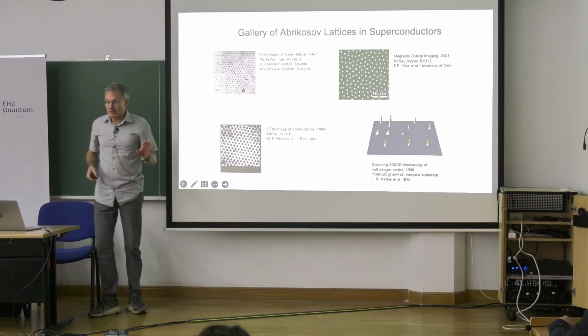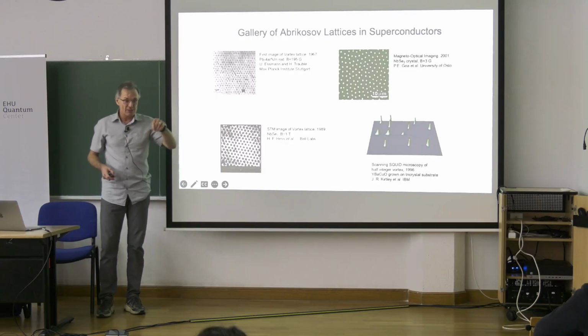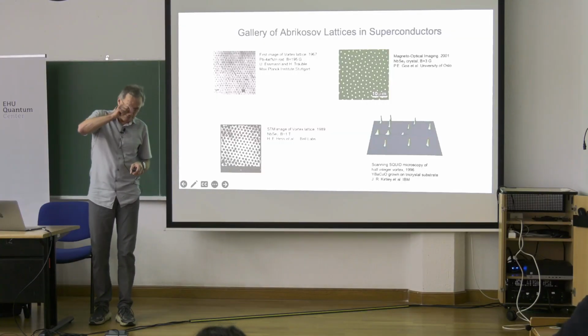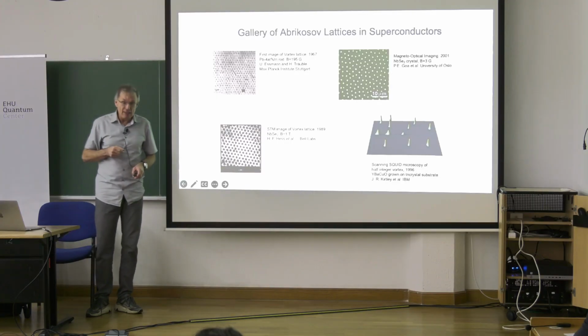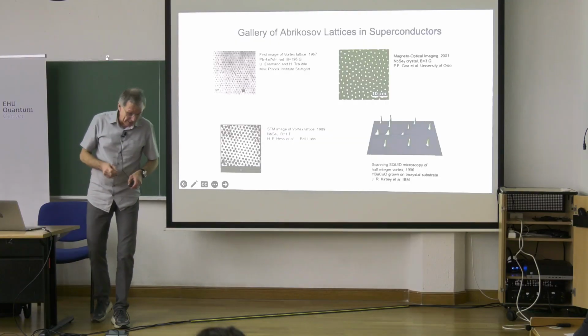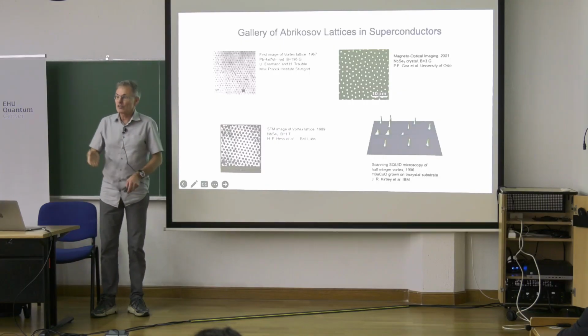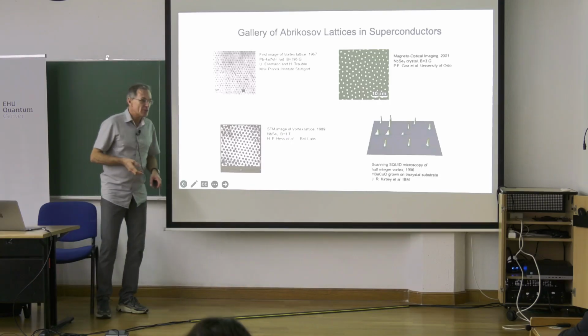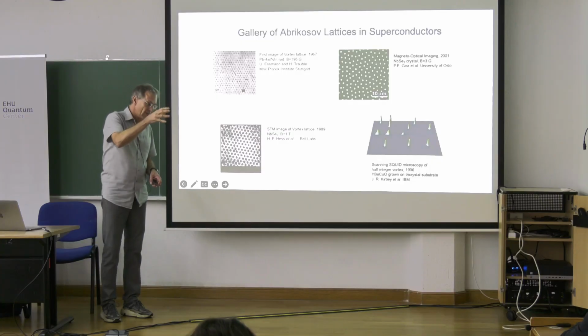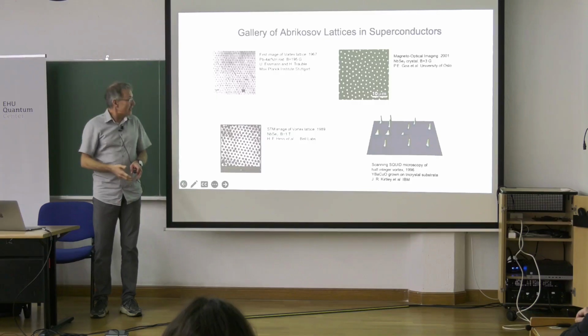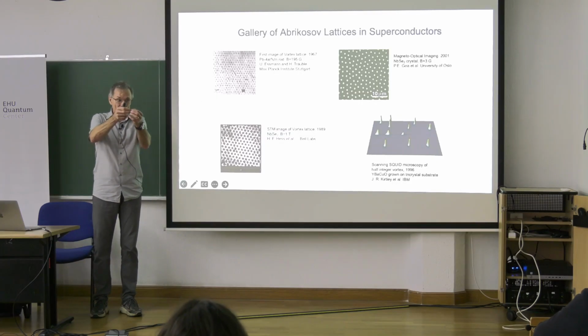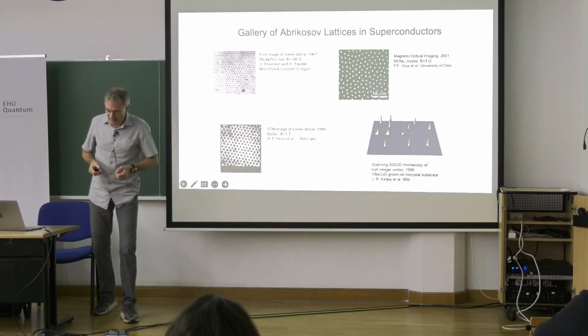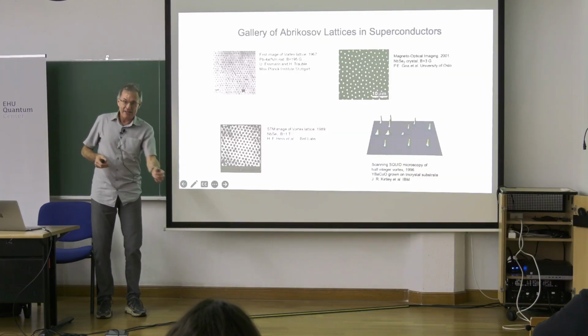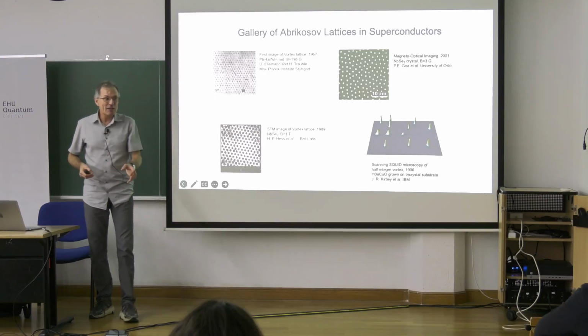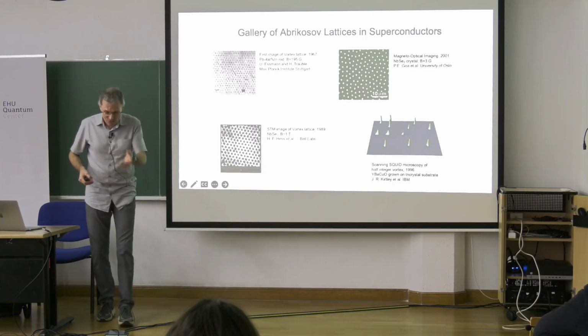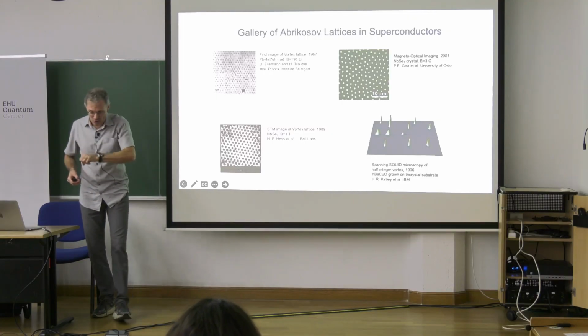It's far from trivial to realize technically, because these magnetic particles, you don't just sprinkle them. In the experiment, you have a Wolfram wire, tungsten wire, like in an old-fashioned light bulb. You push a strong current, which heats it to a few thousand degrees, then it's hot and emits particles, which then come to the surface of your superconductor. So in the same setup, you need this tungsten wire, which is more than 1,000 degrees, and then these particles have to cool down, because if they come with this temperature, they will melt your whole sample, but during the pouring they get cold, and then they eventually land.